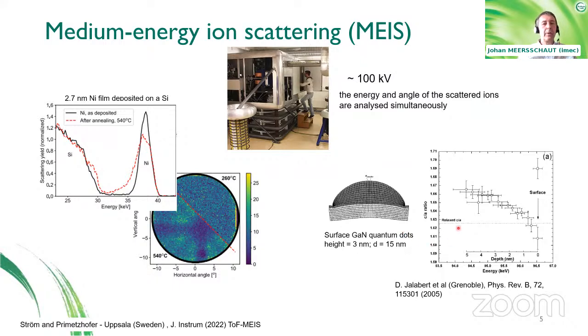And this was smartly used to the benefit in the group of Grenoble, where they investigated the crystalline structures of nanodots which were grown on an aluminum nitride surface. You can see here that a dot of 3 nanometer can be studied with this technique, and even the crystallographic orientation can be derived. In this research, people made use of the mass selectivity of the scattering in this experiment. And they could see that the crystallographic bending depends very much on the depth with respect to the thickness of this nanodot.